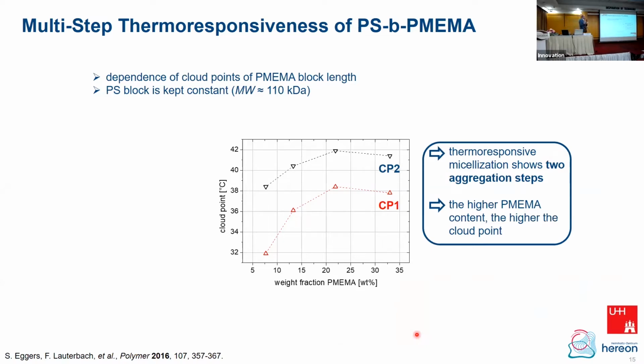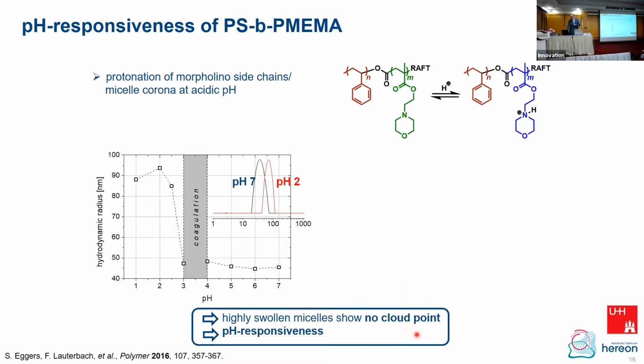Obviously, we have more than one transition. We saw just now two kinds of cloud points, and these cloud points increase with the amount of the hydrophilic block. Both cloud points increase, and the whole system is pH sensitive, what I showed you on the first slide as well. And this is a rather complicated image. You have here the hydrodynamic radius as a function of pH. So at a high pH, we have a low hydrodynamic radius because the N-morpholino ethyl methacrylate is neutral.